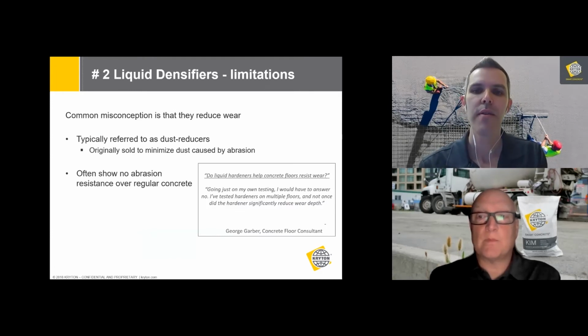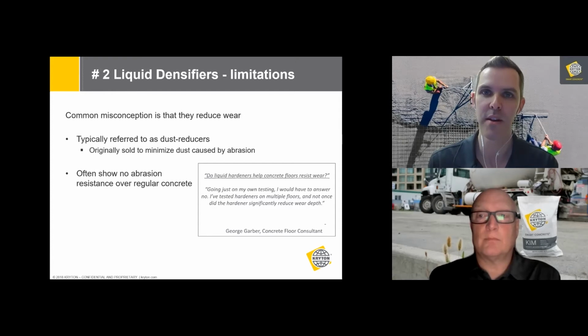Now, the way these products work is they function by reacting with the calcium hydroxide in the concrete. Calcium hydroxide, of course, is a byproduct of cement hydration. And when these products react with calcium hydroxide, they produce more CSH, or calcium silicate hydrate gel. And this is the normal product of cement hydration. It's the good stuff that gives cement paste all of its strength and binding properties and holds that concrete together and really makes concrete concrete.